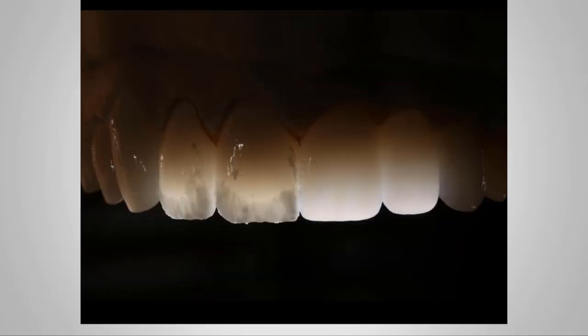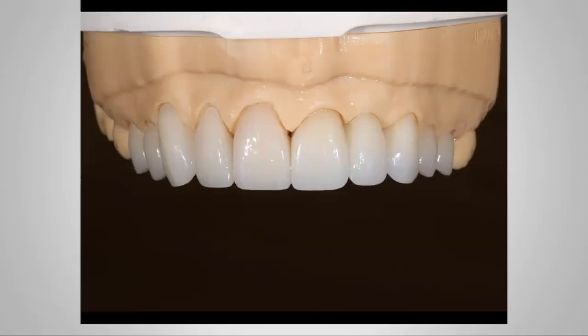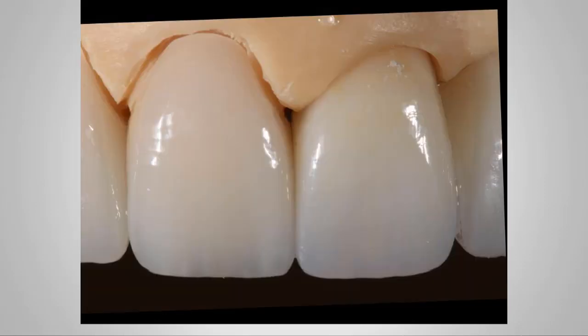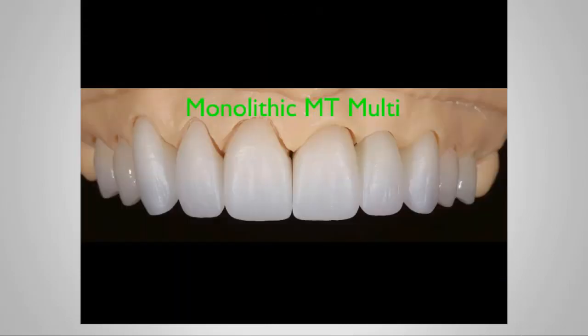So this is the translucency effect that you get from the zirconia and from the lithium disilicate. And once again, really nice effects coming from the zirconia. This is both on the solid model. Close up, you can see at the cervical of the lithium disilicate, we're getting a little bit of show through from the root or from the dentin of the preparation.